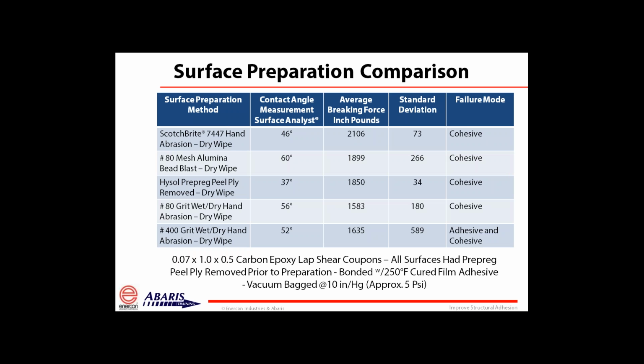At the top you can see Scotch-Brite. Now the first thing I want to do is quantify. These are lap shear coupons that we make in our facility, and then we test. They're about 70 thousandths of an inch thick, 1 inch wide with half-inch overlap in the bond line. They're carbon epoxy lap shear coupons.